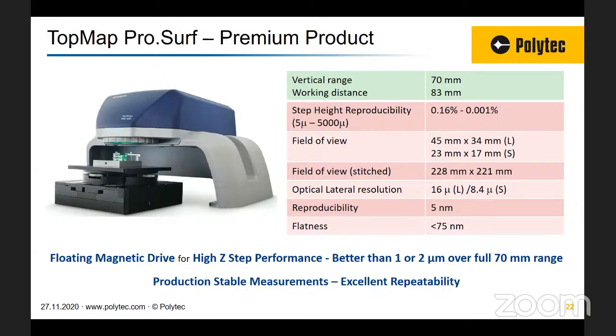So by taking this approach and by using coherent scanning interferometry, we get the nanometer sensitivity, but then we get the low friction force surface. And we have this incredible capability where we can easily measure to 1 or 2 microns step height, reproducibility, and measurement uncertainty over 40, 50, 60 millimeters.